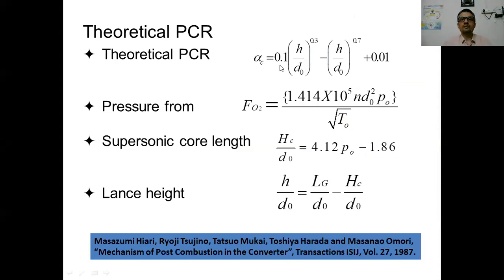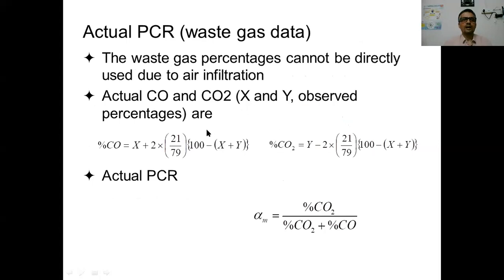So for the theoretical post-combustion ratio, basically this is the lance height, the throat diameter of the lance, where this pressure is being calculated, and the volumetric flow rate of the oxygen is being calculated based upon this parameter. Supersonic core length is being calculated, lance height is calculated by reducing the length of the supersonic core, and the actual post-combustion ratio is calculated from the post-combustion data, the waste gas data, but by considering the effect of nitrogen which is coming after entrainment.